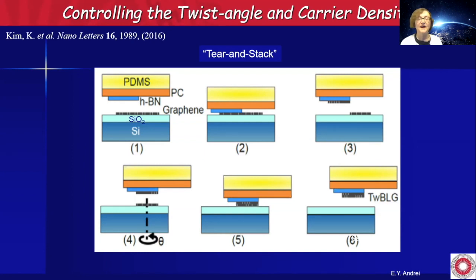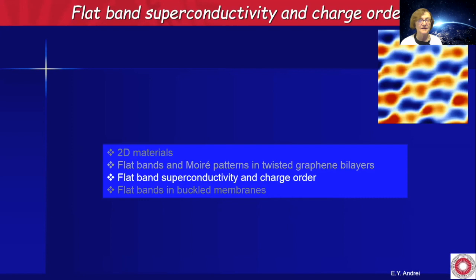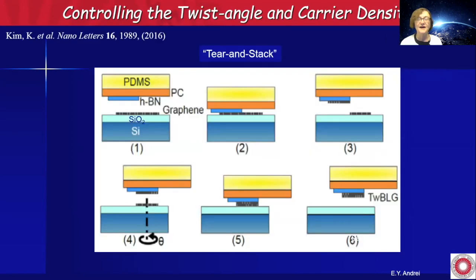You pick up that half, you rip it away from its brother, then you align them again, and now you very carefully can change the twist angle between the two, and then you press it down again. Then you do similar things. You can put another layer of boron nitride or whatever, and you can make a device out of this.